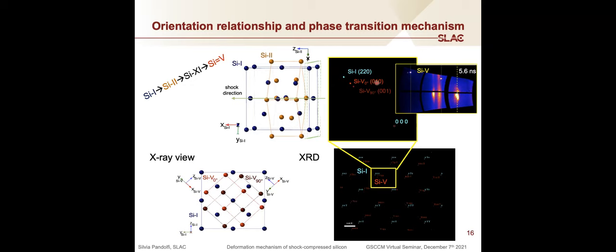Because indeed, the presence of two domains of silicon V rotated by 90 degrees with respect to each other can explain the presence at the same azimuthal angle of a 010 and a 001 reflection that otherwise would have to be perpendicular to each other in the reciprocal space. And it also shows that these reflections are expected to show at the same azimuthal angle as the 2-2-0 reflection of the ambient silicon one phase. So it really shows that this specific deformation mechanism can explain our experimental data and the highly preferred orientation that we observed for the crystallization of the silicon V high pressure phase.